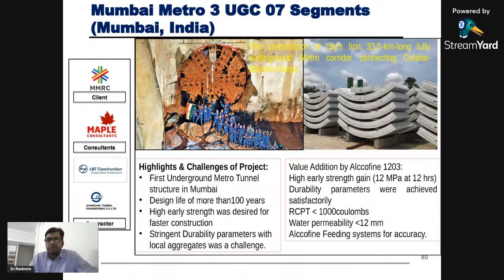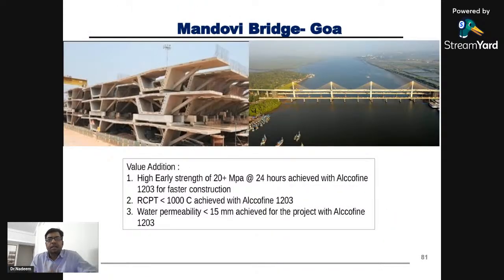For this liner, they were looking for early high strength, 12 MPa in 12 hours, just to reduce the cycle, because it is precast. Naturally, molds have to be used on a regular basis and in a reduced cycle. So the cycle was 12 MPa, 12 hours. Of course, they had a durability requirement of RCPT less than 1000 coulomb and water penetration less than 12 mm. This is how Alcofine is being used for this project. This is again a very good project, the Mandovi Bridge in Goa.